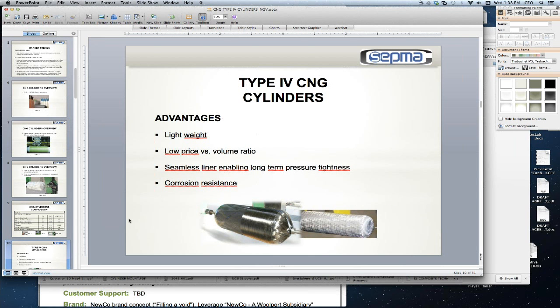So let's look a little bit more at the Type 4 cylinders. Like I said, Type 4s is the plastic liner with typically a carbon fiber resin wrap on top, as shown in the left-hand side picture. The advantages are the light weight, the low weight to volume ratio, basically the ability to carry so much more gas compared to its volume, compared to steel. The seamless liner, which is required by the NGV2 DOT regulations, enables good long-term pressure tightness, meaning that there's no leakage of the gas during service. And obviously the use of composites is really beneficial to the corrosion resistance.